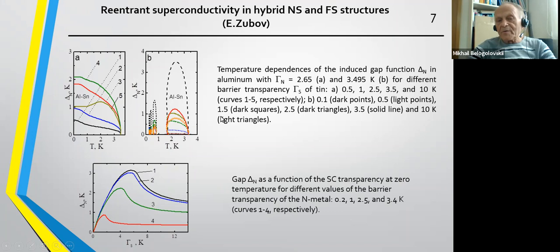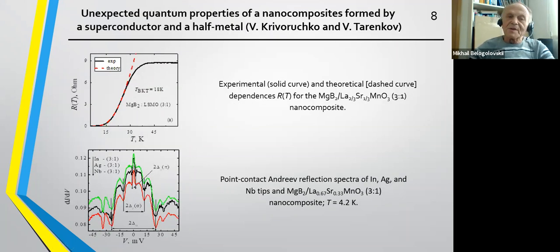But Eduard Zubov showed for the first time theoretically that such a phenomenon can be observed in hybrid normal metal-superconductor and ferromagnetic superconductor structures. So it has not been checked experimentally. In fact, it would be very interesting to verify theoretical predictions in experiment. The second issue within this domain of activities is unexpected quantum properties of nanocomposites, formed by a superconductor with comparatively high critical temperature and a half metal.